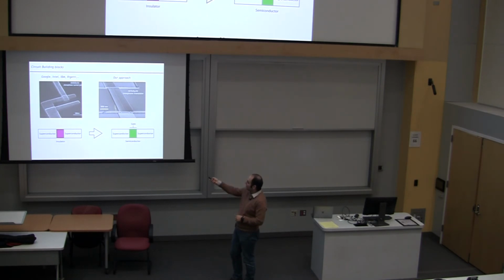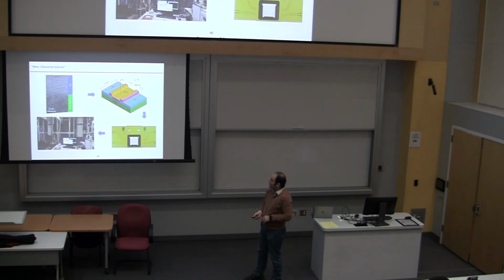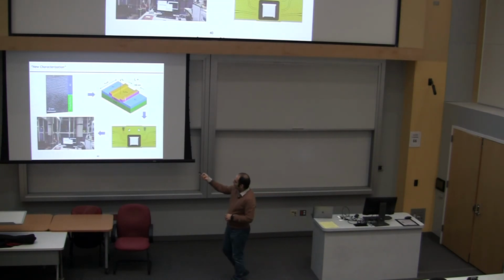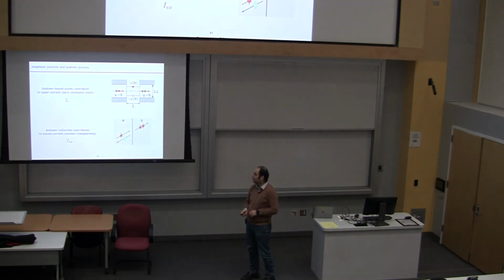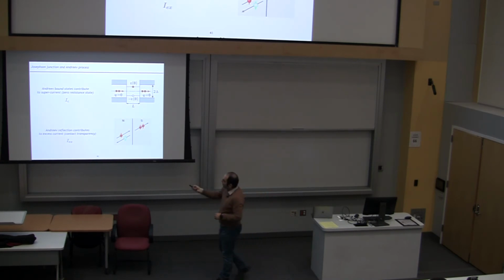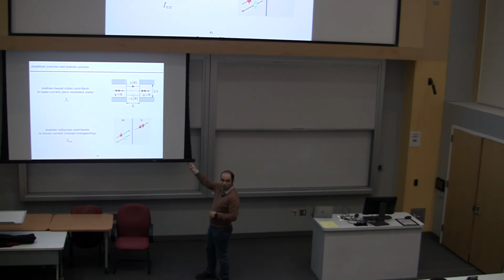So this is an image of our SNS junction, right? This is aluminum, and this little thing is where the aluminum is peeled off, and then you put a gate on top of the whole thing. So the game becomes: grow this, make Josephson junctions with a gate on top, put it in the sample holder, put it in a dilution fridge, and measure them. If you are familiar with Andreev reflection and bound states, these are the superconductors, and this is your indium arsenide channel. The bound states in the junction will carry the supercurrent, that is IC. That tells you how good the structure is.